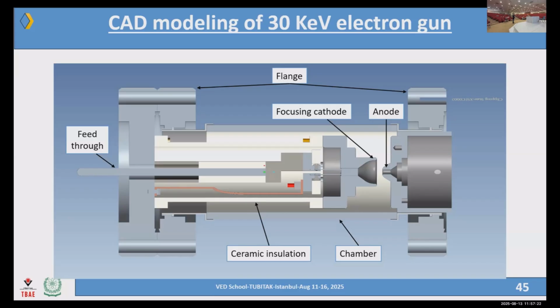Again, the feed-throughs are here. The feed-throughs are meant for providing the electrical signal to this part of the gun. So vacuum feed-throughs are also sealed to ceramics usually. And then you have these mechanical flanges, which are CF flanges for ultimate vacuum sealing. And the whole assembly, of course, operates in vacuum. By vacuum, someone was asking this morning, we try to evacuate this machine up to extreme ultra-high vacuum boundaries, 10 to the minus 9 millibars.